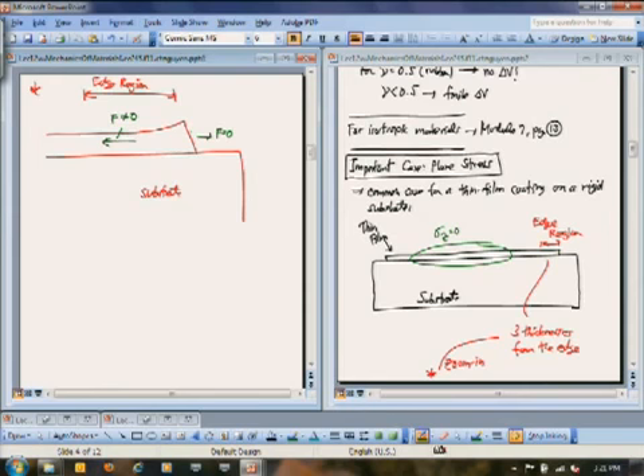Now remember, we talked about the fact that points are places of very high stress. We call that a sharp point. That's a point of very high stress. What you're going to do is develop a peeling force at the edge of this film. And that peeling force is happening because you're at the edge. You don't have any forces going in this direction. You do have lots of forces going in that direction. You're going to create a shearing force that's actually trying to pull that thing up and out. And so when you have too much stress over the top of your substrate, this is why films peel.